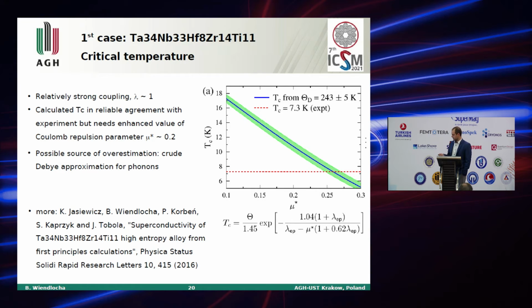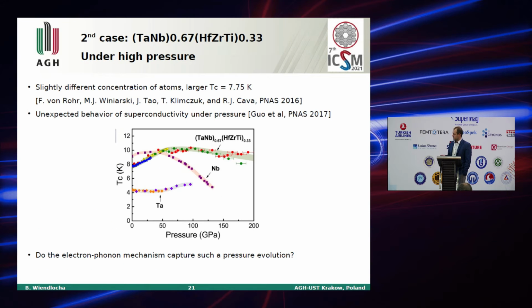And we may say that this material is a conventional superconductor, and the effect of disorder is not very important for its superconducting properties. Okay, the second case which we were dealing with was a similar system: titanium, niobium, hafnium, zirconium, tantalum, with a slightly different concentration. And the interesting thing discovered experimentally for this material was its very unexpected behavior under pressure.